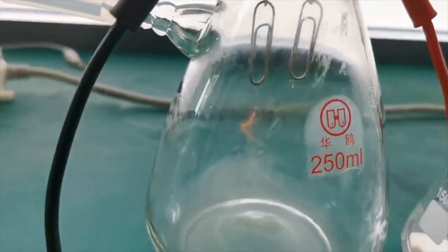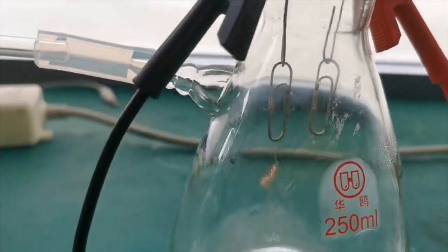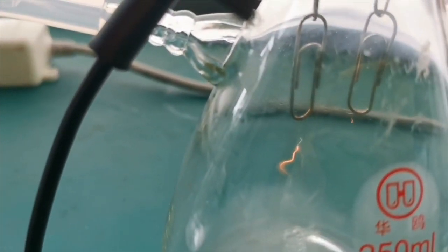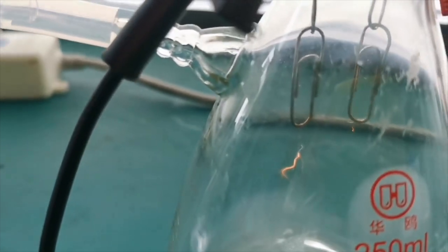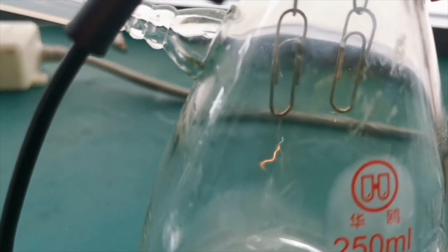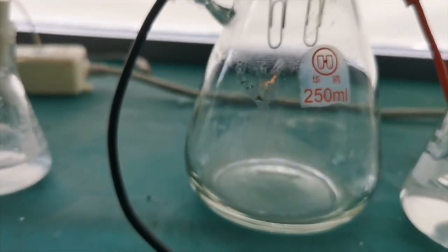Huh, guess what? Our platinum melted. Like, it literally just melted off the sides. You can imagine how hot it was. But guess what? It's still glowing. Which basically means we succeeded. Yeah, the reaction is working. The remaining pieces are still glowing. The platinum wire kept melting and disconnecting, so I have to give it up.